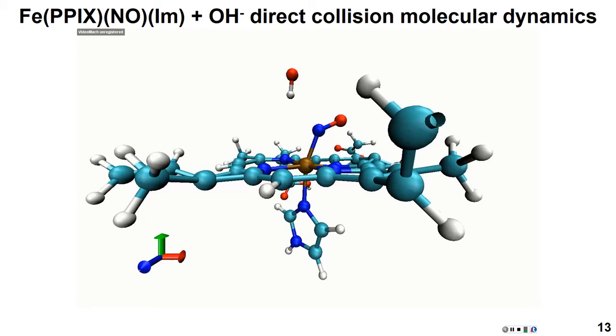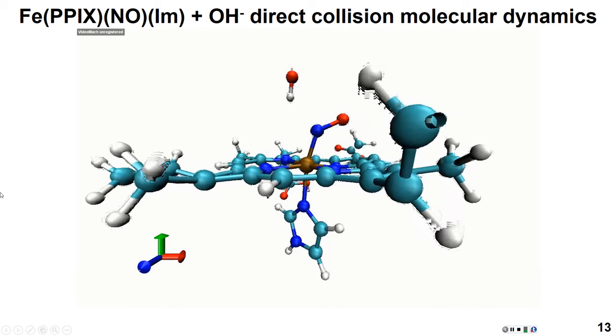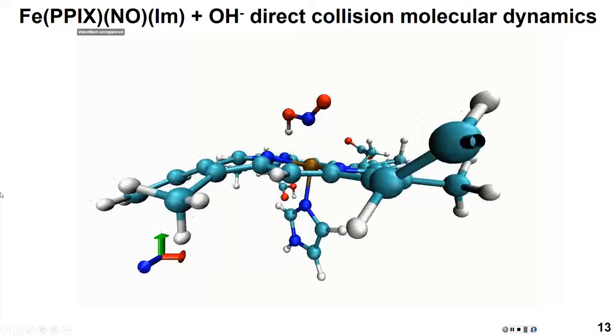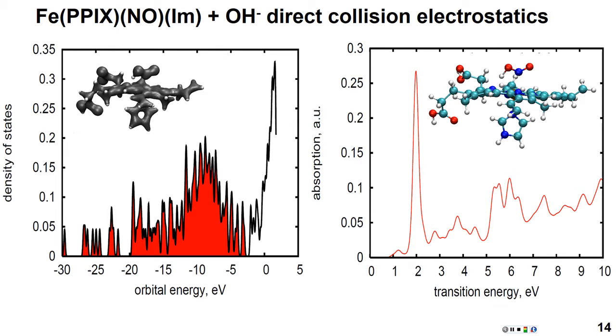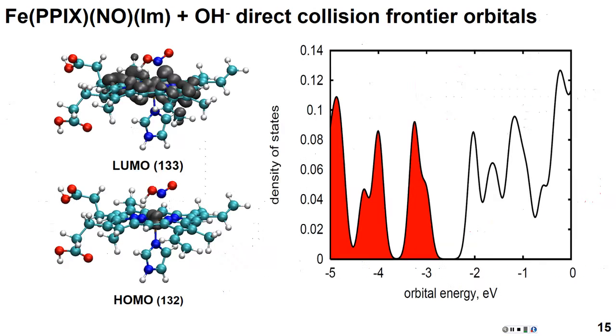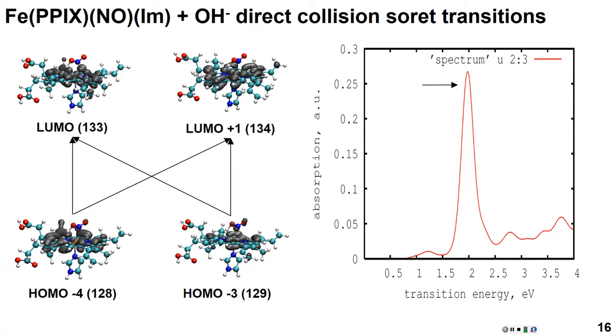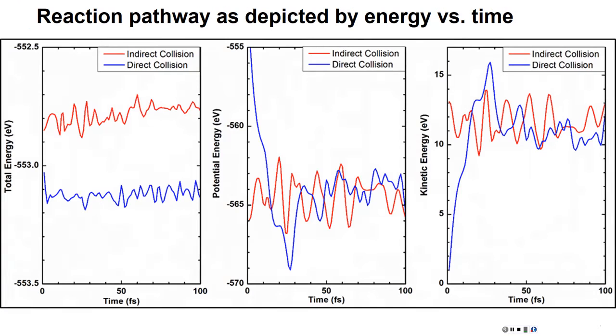Now, when we look at a molecular dynamics simulation where the hydroxide collides directly with the nitrosyl, we've noticed that we've not only connected, we've formed a bond, and it's dissociated from the iron. So we formed our nitrous acid. So what does that look like electronically? Well, our HOMO has some charge density on the iron center, which is slightly different from what we've seen before, and charge density now back on the porphyrin ring for our LUMO. More interestingly, if you recall, with our Soret transitions, those were in the LUMOs partially localized on ligands, and it's not anymore. It's back on the porphyrin ring.